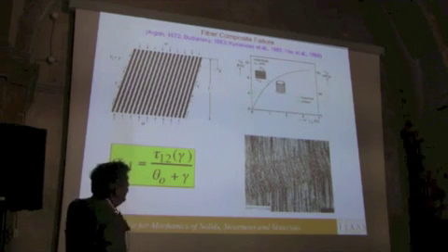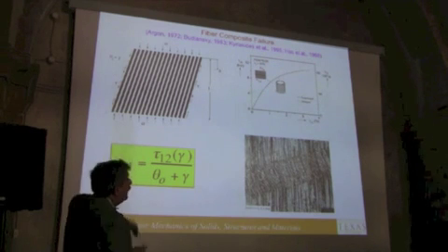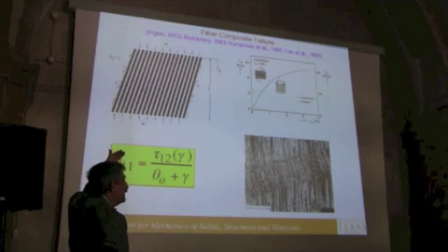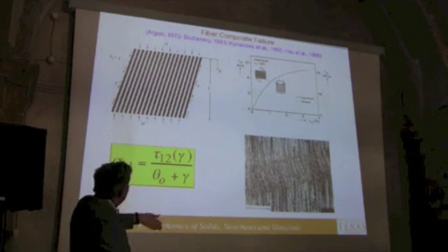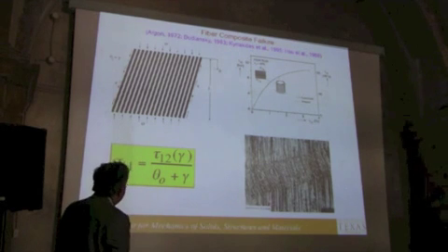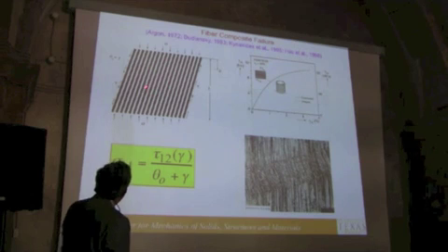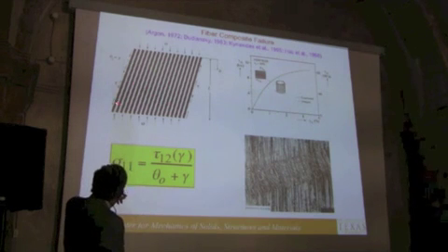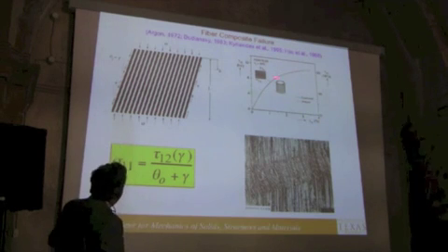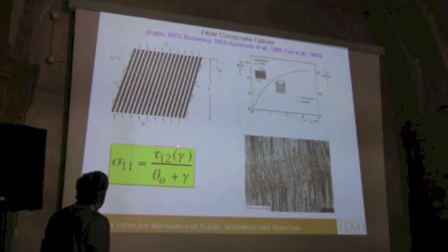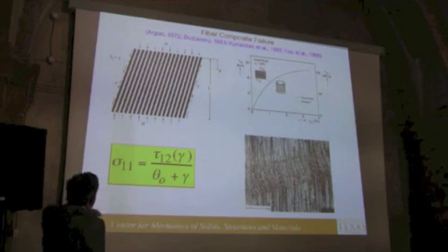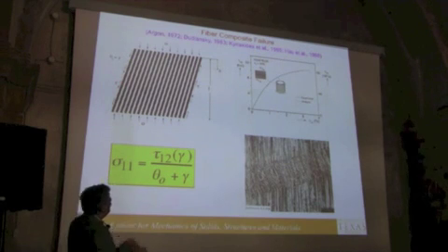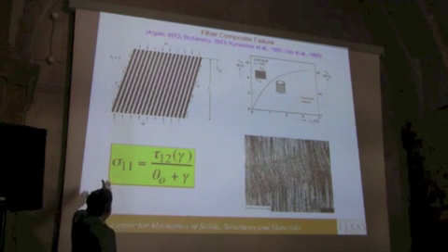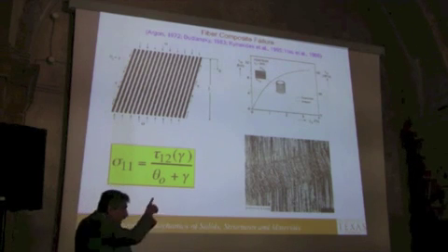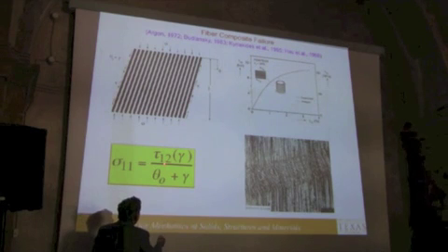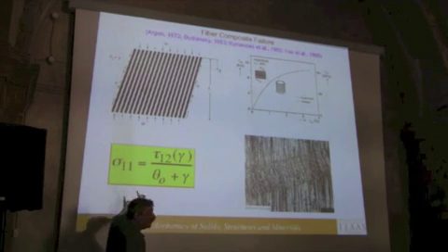So there is a plastic bifurcation that leads to this microbuckling at a very high stress, but because there are always some small misalignments of the fibers, and that's really what this model is showing. It's showing you an idealized composite with fibers and matrix that you compress, and if you put that shear response in here, you just do equilibrium in here. Theta naught is the initial angle of misalignment, gamma is the additional shear that you get, and this is the axial stress, and this leads to a limit load. This is nonlinear, and this is geometric nonlinearity. This leads to a limit load.